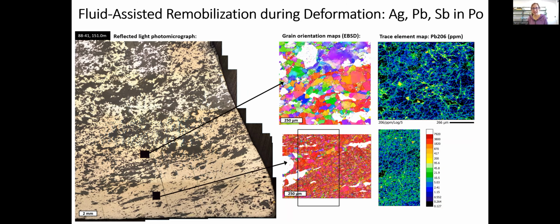Now, this sample can actually also show us an example of fluid-assisted remobilization. So here we have the same EBSD maps as before, but now I'm comparing them to compositional maps for lead. And you can see that the lead pretty much outlines the pyrrhotite grains, especially over here. You can see it really nicely. There we have lead outlining a grain with lead along a stripe through there. That's this grain and this subgrain boundary. So lead is sitting on grain and subgrain boundaries. And we see the same thing for silver, antimony, and sometimes also for bismuth.